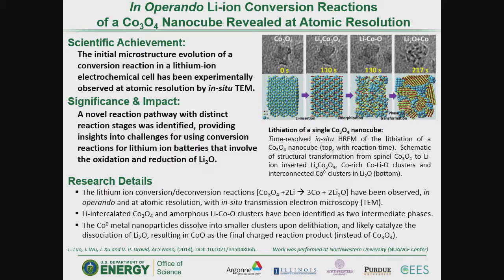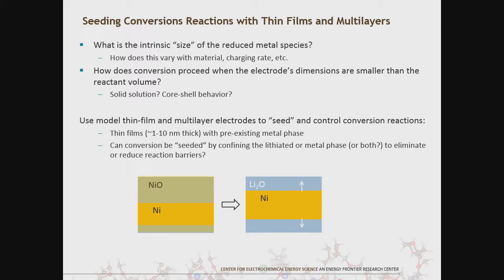This is cobalt oxide, where the initial phase is insertion, and then eventually the material actually changes morphology until you get nanoparticle formation. So we'd like to see what we can do with that.